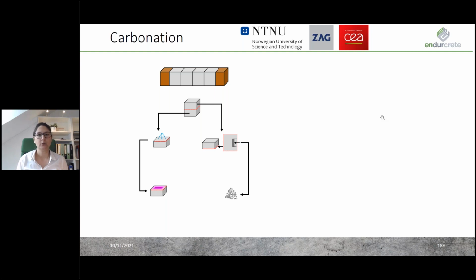Of the prisms, we know the cement composition for sure, we have a cement producer on board in this project, but also the mortar and concrete recipe or mix design. So aggregate types, particle size distributions, the water to cement ratio, the admixture content, all of that was known. So half of these prisms we cut into thick blocks and we carbonated them at 60% relative humidity and 1% CO2 concentration for various times.